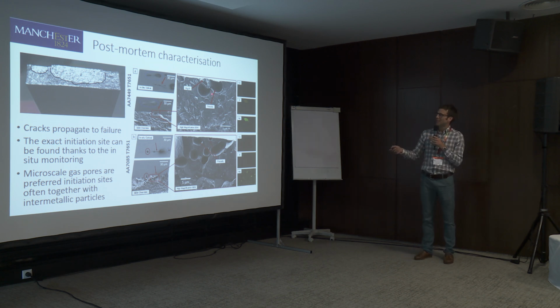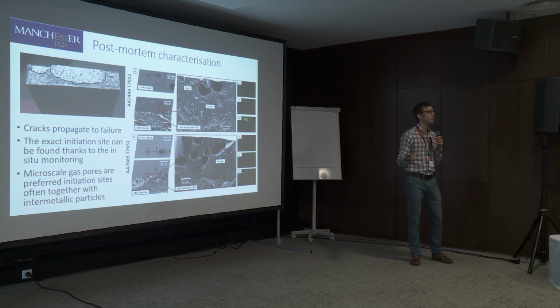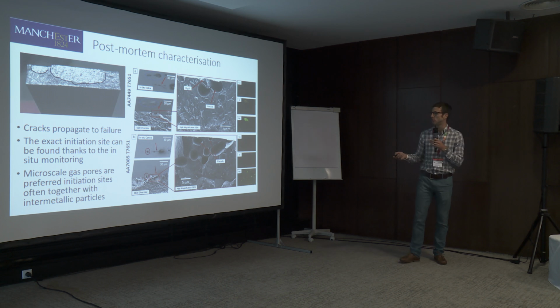We can also see that Mg2Si is really important for these initiation sites in the 7449 material as well. But really, these clusters are creating quite vulnerable metal ligaments in the metal to form these initiation sites.